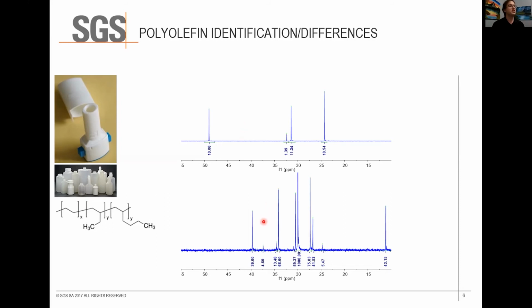The lower spectrum here is a linear low density polyethylene. So you have a long sequence of straight ethylene, and then you may have occasional branches intentionally added. Different branch types give you different shifts here, and so you can actually back calculate that. This is a linear low density polyethylene that has about 1 or 2% 1-butene copolymerized in.